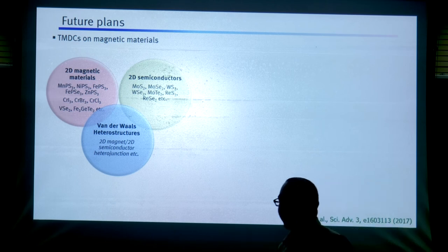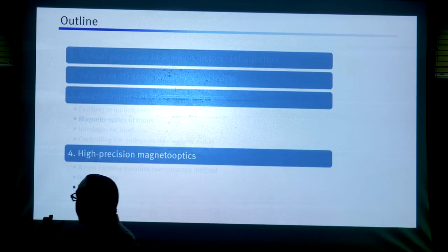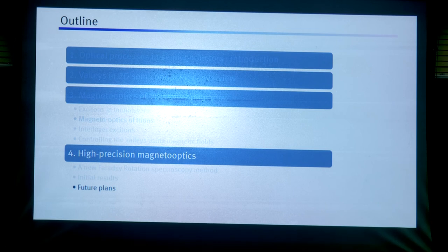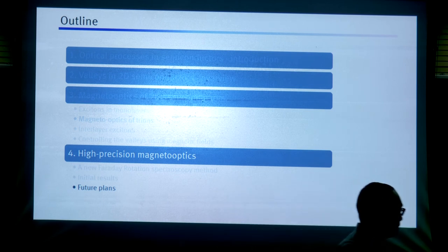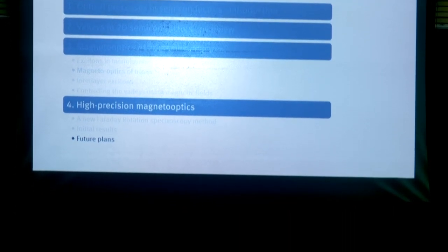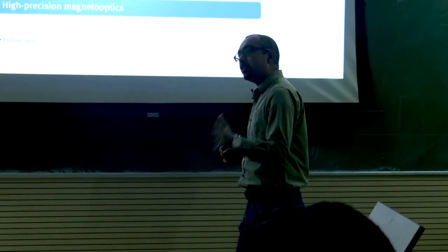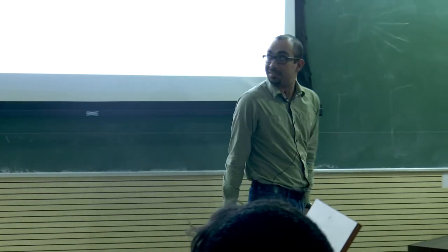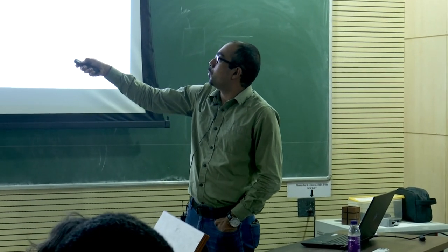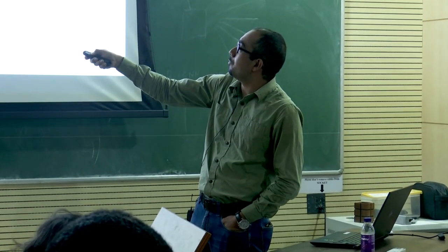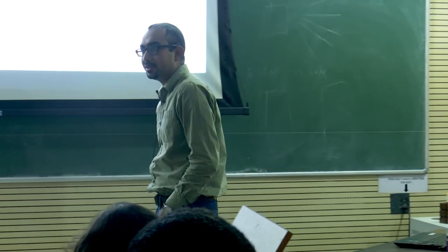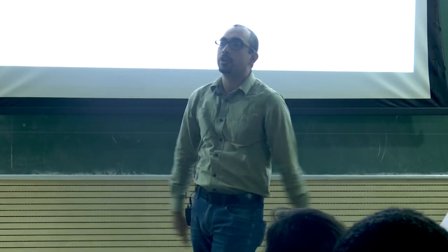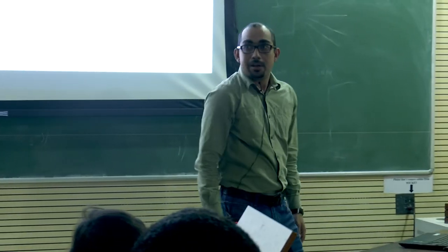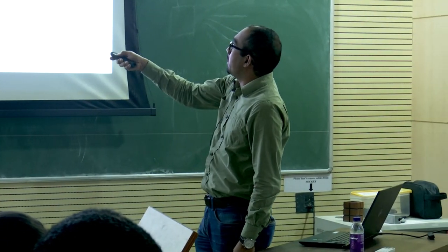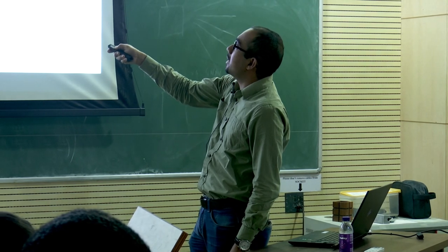Now, my question was, if all of this which I was telling, tuning the population or tuning the phase, if we can do it with small fields, is that possible? First of all, we have a technique now, we can just measure that effect. But can we tune that as well? The answer is this. If we have some two-dimensional magnetic materials which make the substrate of these two-dimensional semiconductors, meaning if we create interfaces of 2D magnetic materials and 2D semiconductors, then it's found that there is a strong field at this interface already.